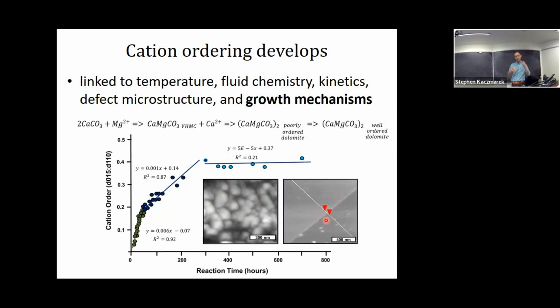And so we've used this data to infer different growth mechanisms. The material here is growing sort of very sporadically, material adding to the crystal surface in kind of an unruly way. Whereas later on, it's much more deliberate, growing by what we'll call a layer growth mechanism.